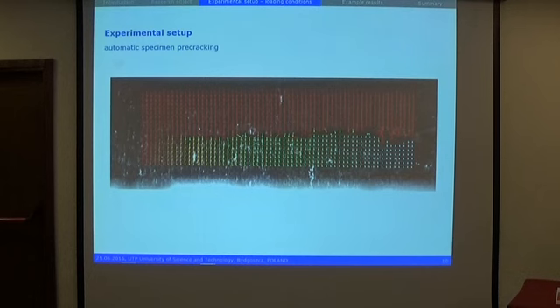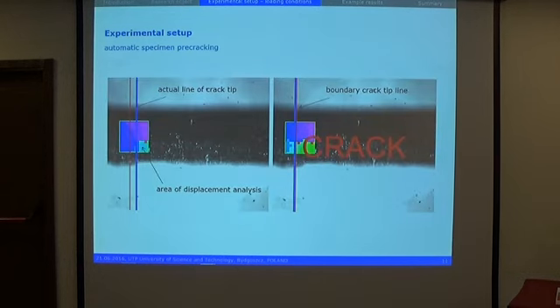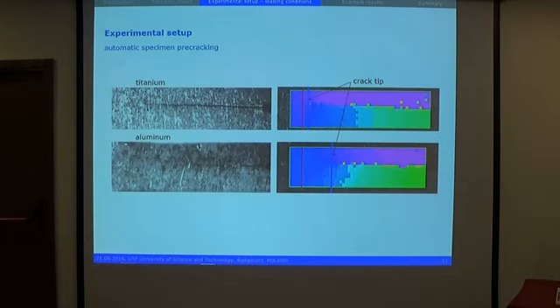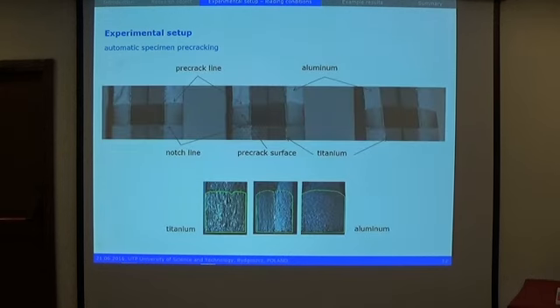So this procedure was involved in the computer code for system control, and after achieving the required length of the crack from one or the other side of the specimen, the system was stopped, and we obtained the specimen with a very similar length of the initial crack. But of course, the problem still exists that we have a different length of the crack in the titanium and aluminum. After the tests, we have compared the crack line in a few specimens.